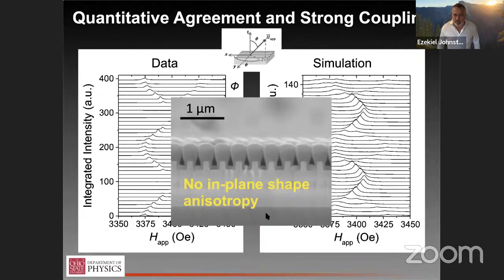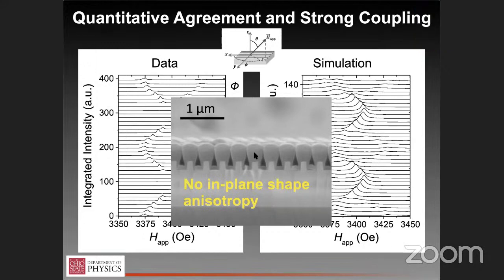So as a technical detail, for people in the audience who have studied magnetism, these 3D structures look kind of like nanowires. And in fact, we see an in-plane magnetic anisotropy. That's initially intuitive, but then we realize the length scale of the density of the packing here is such that from a magnetics point of view, this should act like a thin film. There's not going to be significant in-plane demagnetizing field, yet we still see an in-plane anisotropy. And in fact, the easy axis for that is oriented perpendicular to the long axis of the wire, perpendicular to the direction that one would expect to see.